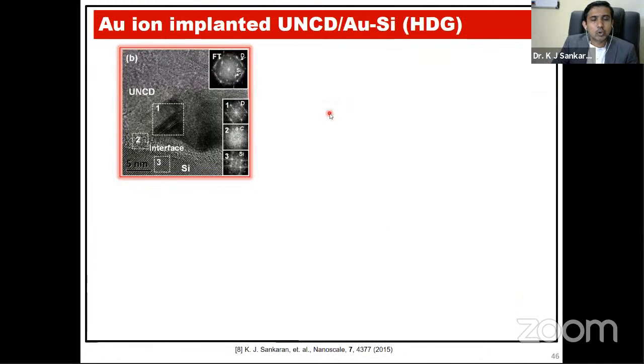So this is the gold ion implanted UNCD grown on silicon substrate. You can see that the gold ion implantation enhances the field electron emission properties of films grown on silicon. But at the UNCD and silicon interface, you can see there is the presence of amorphous carbon. Even in the grain boundaries, we saw amorphous carbon when the films were grown in methane and argon plasma. So we removed that amorphous carbon from the grain boundaries by incorporation of nitrogen, and also by gold ion implantation.